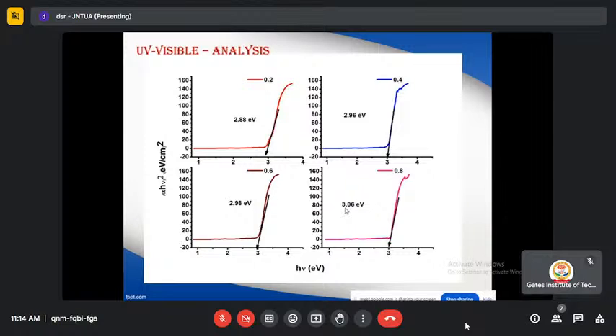Coming to the UV visible analysis, with the help of this UV visible spectrometer, we can find out the optical band gap of the synthesized samples. The optical band gap energies of the samples synthesized by varying the cobalt composition from 0.2 to 0.8 were determined, taking the linear portion of the curve in the direction of the x-axis as the absorption coefficient alpha approaches 0.